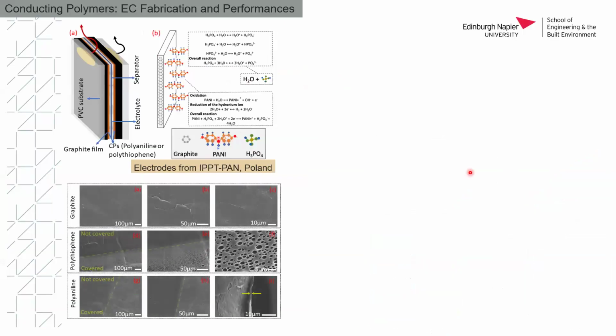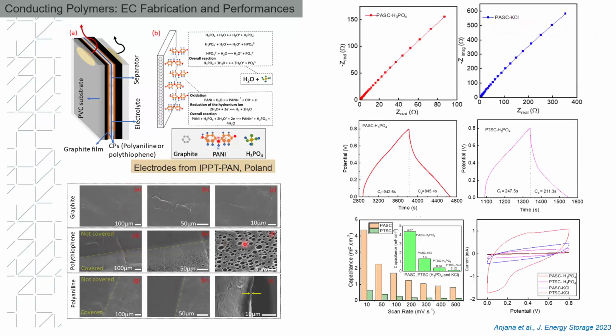Another case study: you can see here that we collaborated with another institute in Poland, where we investigated the performance of a conductive polymer, as I mentioned previously. For example, we coated by spin coating on top of graphite a polyaniline or polythiophene based conductive polymer. And once we coated this, we noticed that depending on the type of the polymer and the type of the electrolyte we are using for the electrochemical application, the performance varies.